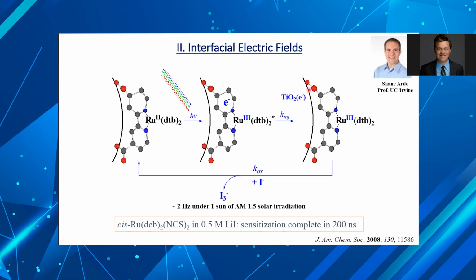What Shane found, and others as well using the charge extraction technique, is that at the power point in a 20 nanometer TiO2 particle, there are roughly 50 electrons residing in there. And on a 20 nanometer particle, there are about 500 dye molecules, just to give you an idea of the stoichiometry. For a long time, people thought those electrons didn't do anything. They didn't generate an electric field because of the dielectric constant of the electrolyte and the permittivity of the TiO2. It just screened the field.